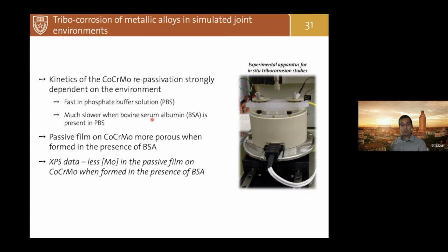We could correlate friction and the electrochemical potential, and there's also the impedance spectroscopy measurement that we carried out. And what we could observe is that the kinetics of the repassivation of cobalt, chromium, molybdenum was very fast only in the buffer solution without any albumin. Whereas if you have albumin, proteins in the buffer solution, the repassivation kinetics is much slower. And also the passive film was much more porous. This is an important problem to look at since it will also impact the mechanical properties of the passive layer and the potential wear resistance of the passive layer over time.